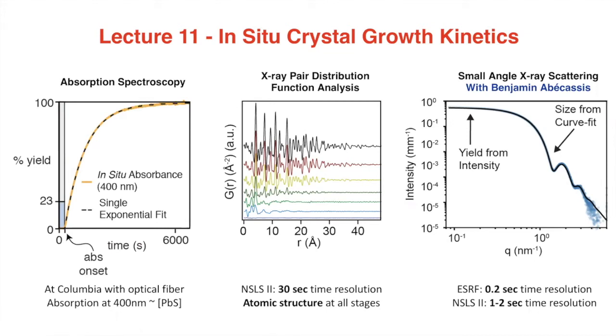And it turns out it has this sort of wiggling pattern here, and those wiggles are related to the shape and to the size of the object. And you know, because our crystals have very, very narrow size distributions, you get these wonderful clean wiggles. If you had a mixture of different sizes, you wouldn't see wiggles at all. You'd see some sort of a smear, but not in our model system.